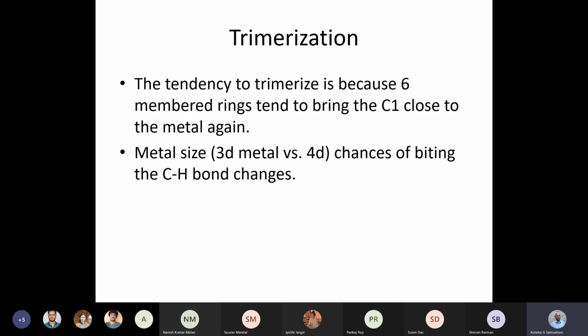Okay, so the general explanation that you find in many of these cases is that the tendency to trimerize is because six-membered rings bring C1 close to the metal again. I find that difficult to believe because nickel does it in the second step itself. If you see the catalytic cycle, at any step after the first insertion of the alkene, you can have beta hydride elimination. Beta hydride elimination could have happened at any step, but in the case of chromium, it happens after 3 ethylenes are stitched up. In the case of nickel, it happens after the second ethylene is stitched up. That's the place when you have a saturated hydrogen available for the metal to do beta hydrogen elimination or a reverse migratory insertion.